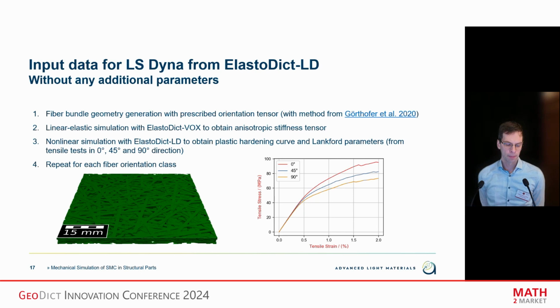What you need to do is generate your fiber bundle geometry, where you can prescribe a specific orientation tensor. You can perform linear elastic simulations to obtain anisotropic stiffness tensors. You can perform tensile tests in 0, 45, and 90 degrees. And from those, you can directly get your plastic hardening curves and the Lankford parameters. And then you can perform these kinds of calibrations for each orientation class which you want to consider in your component.